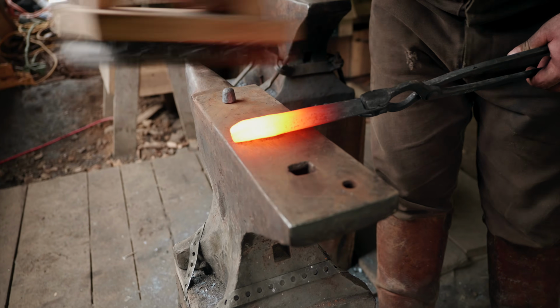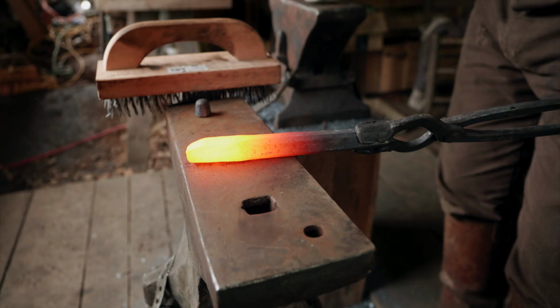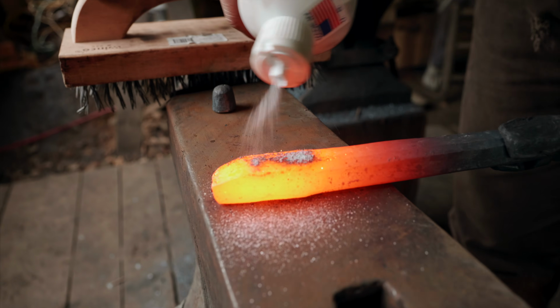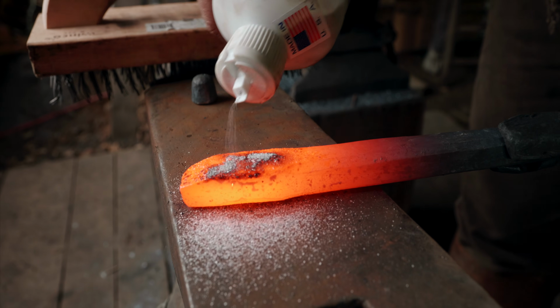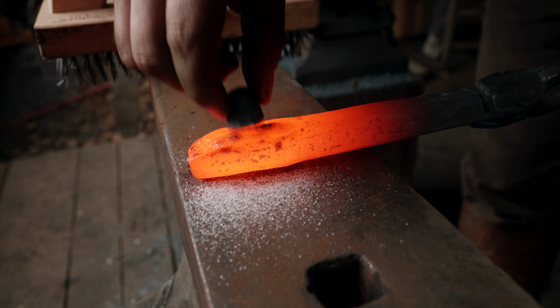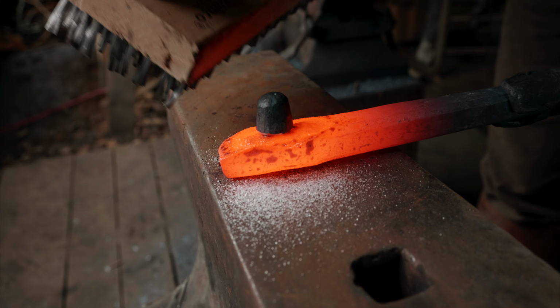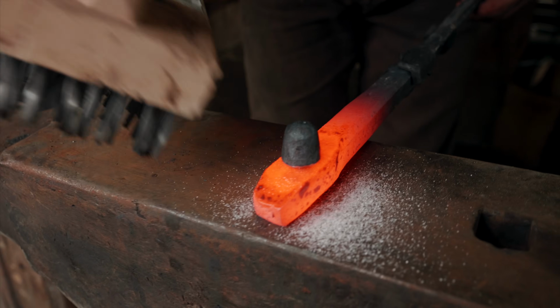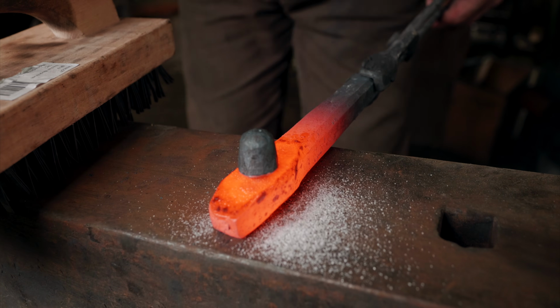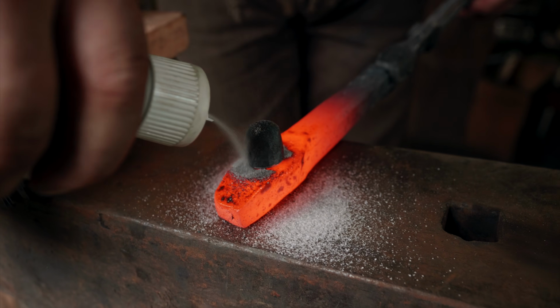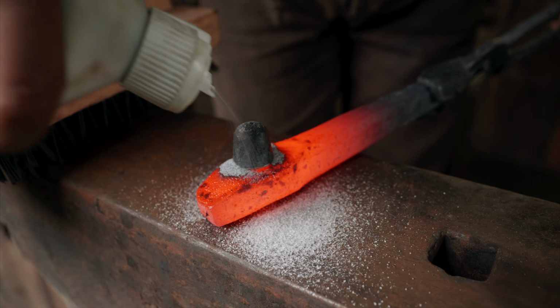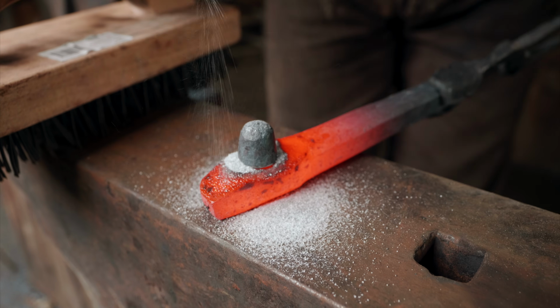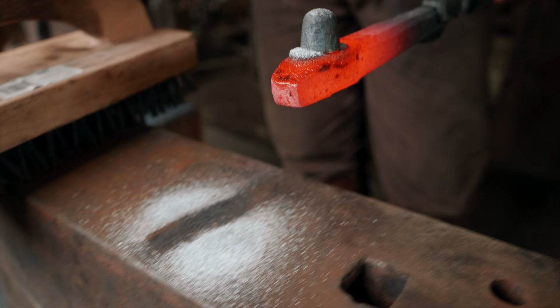So I've heated this up, and we're going to flux it in preparation for the forge weld. I usually use borax for forge welding flux, but I'm using Iron Mountain forge welding flux today, which is good stuff. All right, we're going to try to get this centered in here, and I'm actually going to squirt a little extra flux around there, kind of try to hold it steady. I'm not going to arc weld it, but if you wanted to, a tack weld from an arc welder would help keep that from moving.